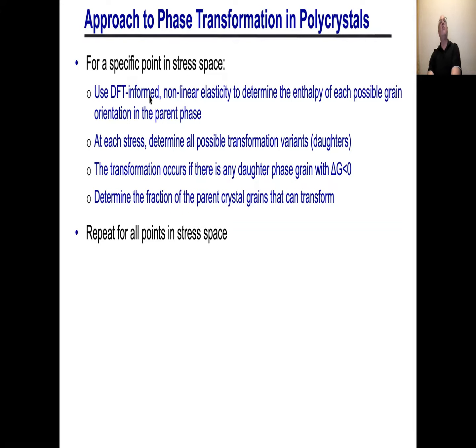So how are we going to do this? What we do is we calculate the third order elastic constants using DFT. Then for a particular point in stress space, we determine the enthalpy of all possible grains in the alpha phase under that specified point in stress space. And at each of those points, we look at all possible transformation variants, all possible daughters, given the orientation relationship. And we say, do any of them have a change in free energy which is negative? Okay, and if it does, that says it can transform. So at a particular point in space, I'll have, say, 35 different orientations of the alpha phase that can transform, and it'll transform to any of those daughter grains. Okay, and I can repeat this for all points in stress space.